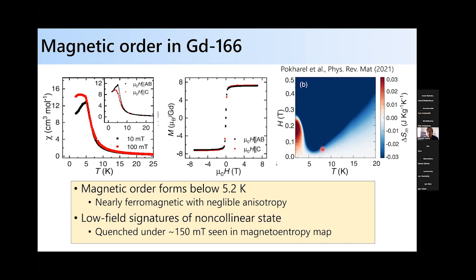But then if you look at a magnetoentropy map using the Maxwell relations from susceptibility data, one can see that there's some type of feature at low temperature in the ordered state around 0.2 Tesla. It's an entropy anomaly. And you usually see this in a lot of non-collinear ground state systems, where in the low field state you have a non-collinear state that gets easily polarized. So there seems to be some feature that's quenched under about 150 millitesla in this magnetoentropy map. So we wanted to try and understand what the zero field ground state is.